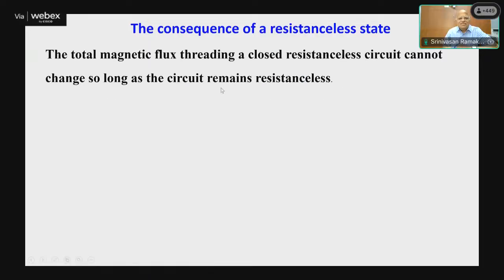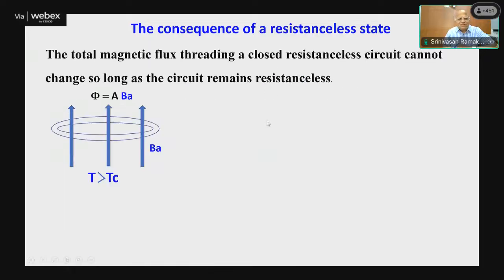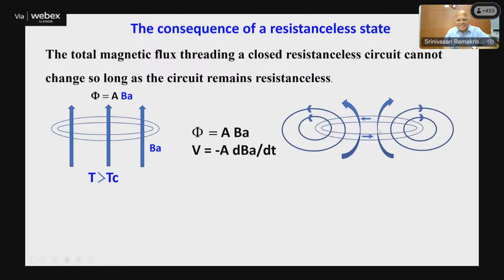What are the consequences of a resistanceless state? Immediately, you see that the flux threading the circuit cannot change as long as the circuit remains resistanceless. How do you see this? Let's take a small ring, and say this material is right now in the normal state where T is greater than Tc. The flux threading the circuit is the cross-sectional area times the applied field, and this will induce a voltage which is minus A dB/dt. Now if you cool it below Tc, you will see that the flux inside is constant.